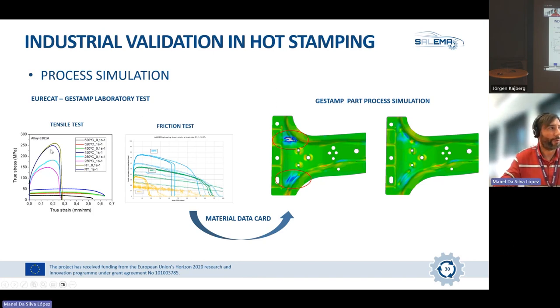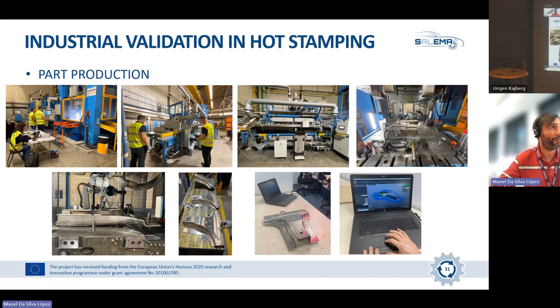and that's what was done with the data extracted from Eurecat tests and also some tests done by Gestamp: tensile tests at different strain rates and different temperatures, and also friction tests carried out at Gestamp. The simulation of the demonstrator was performed. Some critical areas were found that were solved with just some minor changes, and with that data, the tool was manufactured and the production of the demonstrator was done.